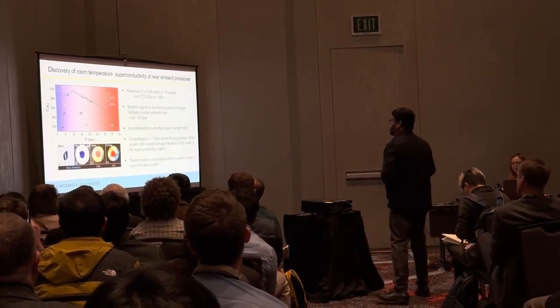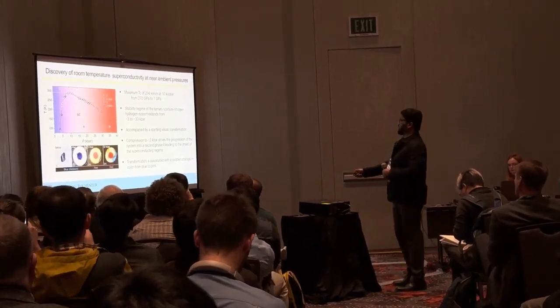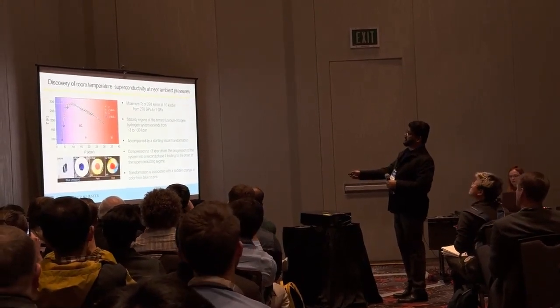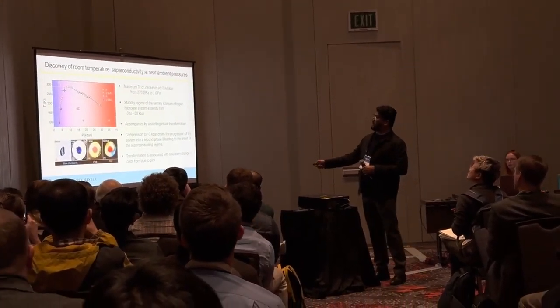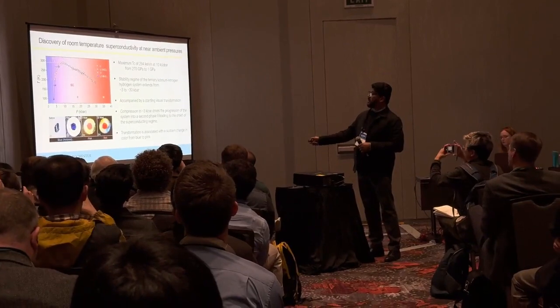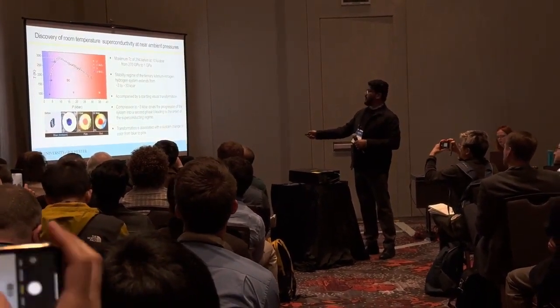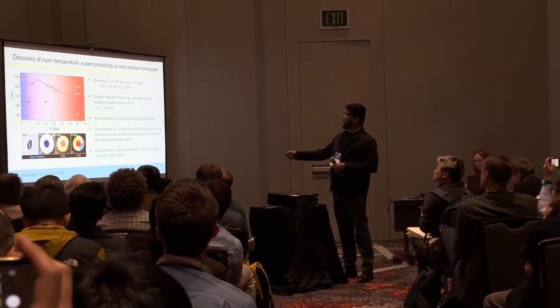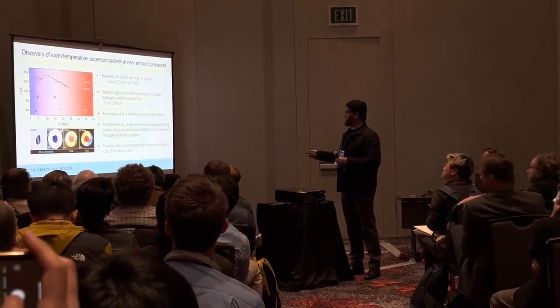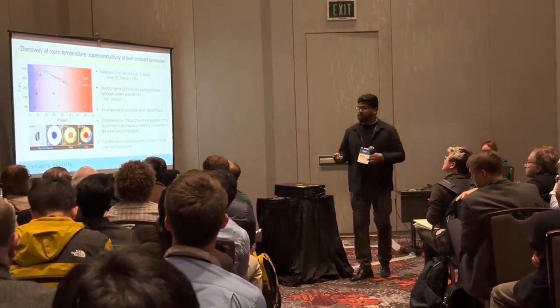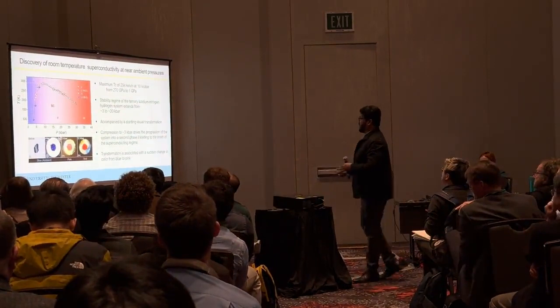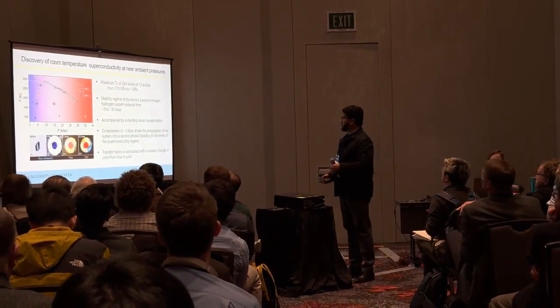So in summary, you see the superconducting transition as high as room temperature at 10 kilobar, and this is when the sample becomes a pink color material, blue to pink to red. This is where you can see the high superconducting transition. So this also goes very closely with the color change, and the stability range is 3 to 32 kilobar.